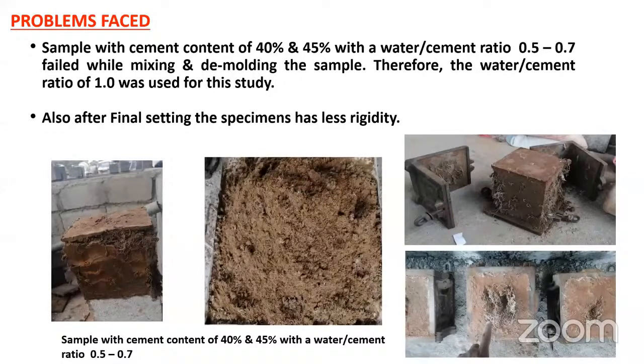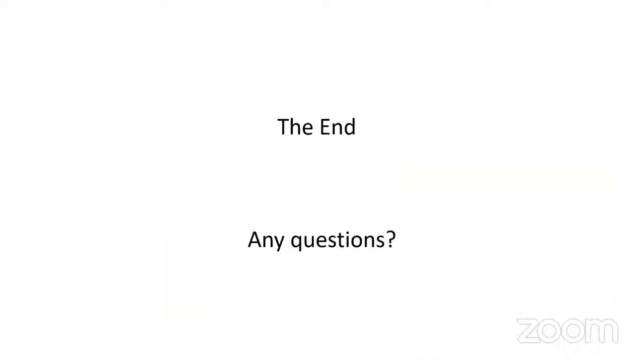Also, after final setting, the specimen had less rigidity as shown in this figure. This figure shows the sample with cement content of 40% and 45% with water-cement ratio of 0.5 to 0.7.